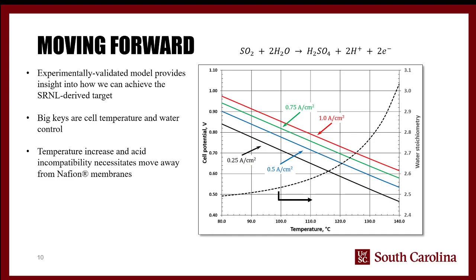Because what happens is, as the water vaporizes, more of it tends to stay in the vapor phase as it flows through the cell, which means that the acid concentration locally on the catalyst goes way up. And it turns out that sulfur dioxide is actually less soluble in more concentrated sulfuric acid. And so effectively what you have is you get a lower amount of reactant at your electrode, which means that your current density tanks.